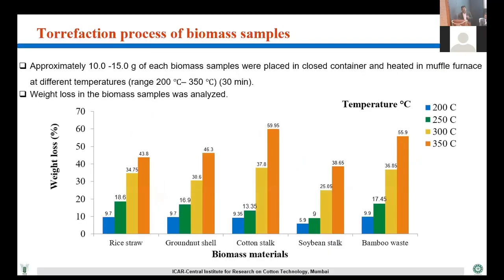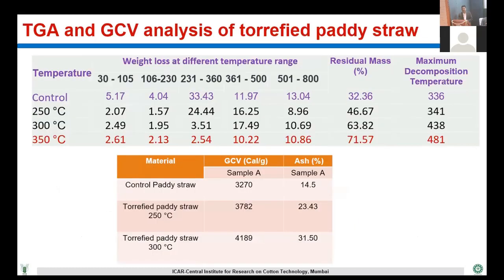Our institute is working on torrefaction of biomass materials, and we are using different biomass like rice straw and groundnut shell at different temperatures. Initially we are getting some success in optimizing this torrefaction process. Here you can see that the control paddy straw has an initial GCV value of 3270. When torrefied at different temperatures like 250 degrees Celsius, it goes to 3782, and at 300 degrees Celsius, it is nearly 4200. So the GCV value increases by nearly 20-30% when you torrefy these pellets.